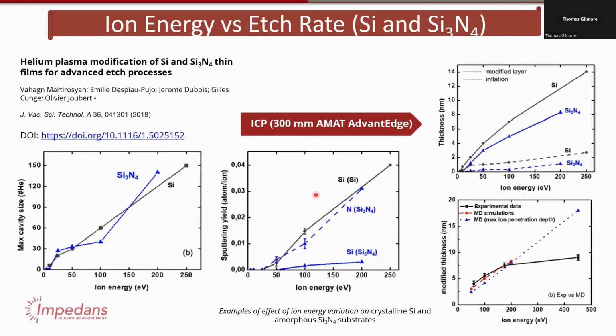One other practical example, just to show you this. This is for silicon or Si3N4. You get the same idea. There's some cutoff energy, and then once you go above that, you start etching. Okay. So the message here is not only does the ion flux matter, but the ion energy matters. And both of those can drift in a process. So that gives us challenges in process control.